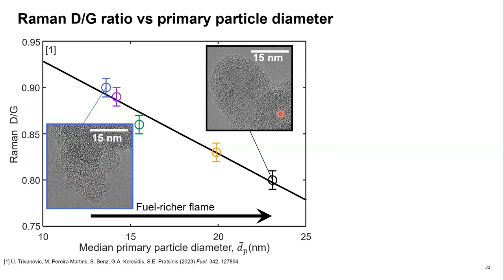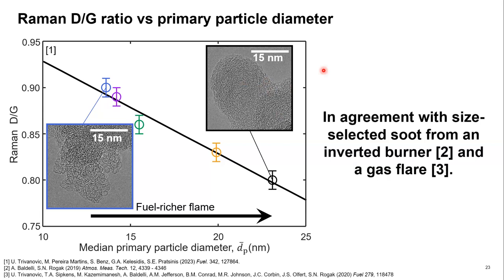And this is probably because of the increased amount of surface growth that was required to make these significantly larger primary particles. And this is not the first time that such a correlation has been observed. This is in agreement with literature which size-selected soot from an inverted burner and showed that even within a single flame condition, this sort of correlation held, and also with work looking at similar conditions in a gas flare.